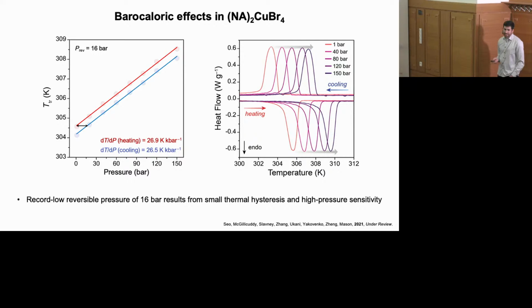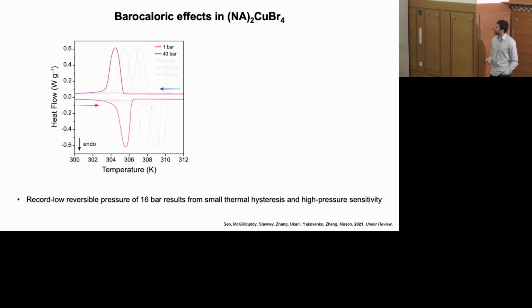And what we were most excited about with this material is that because of the really low hysteresis, we can actually drive phase transitions reversibly at really low pressures. So pressure now of just 16 bar. For reference, most of the barocaloric materials that have been reported in the literature previously required pressures on the order of thousands of bar to operate reversibly. So this is something we're really, really excited about.